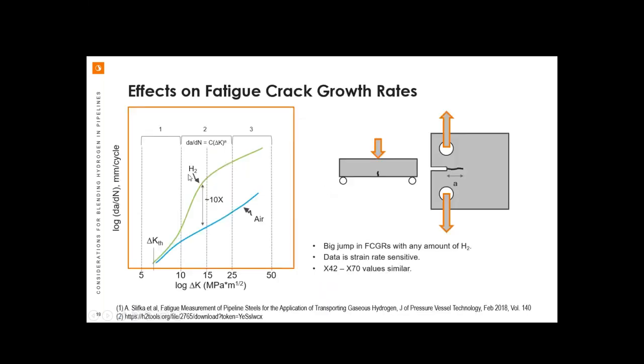So then I'm going to go back to some data. This is just a sketch of data you can find in the paper below. This is from a group that actually provided test data for the ASME B31.12 code body. The sketch shows that we have this roughly linear response of the fatigue crack growth rate, so millimeters or say inches per stress cycle. And it's growing, and this is on a log plot. And I will say that, based on this paper and other references, what we see is that if you're X42 or X70 pipeline steel, it doesn't seem to matter. All the data seems to be grouped around this blue line.